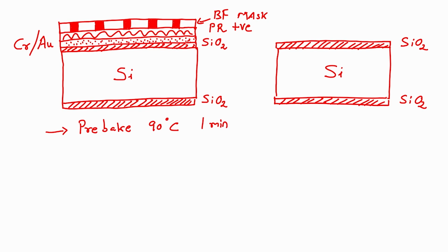That means let us start from scratch. Oxidized silicon, that is silicon dioxide we have grown, on that we have deposited chrome gold, and we have spin coated photoresist. After photoresist we will pre-bake at 90 degrees, then we will load the mask and do the hard contact. Hard contact means the two are touching each other, alright. Mask is touching the wafer spin coated with photoresist. This was easy, very easy.